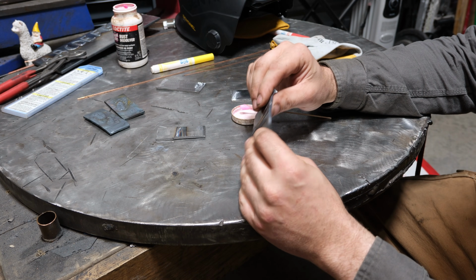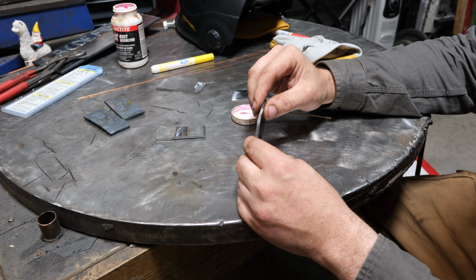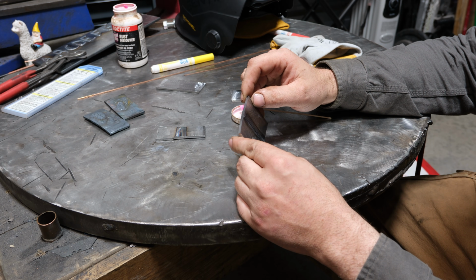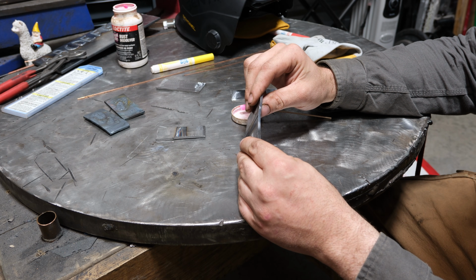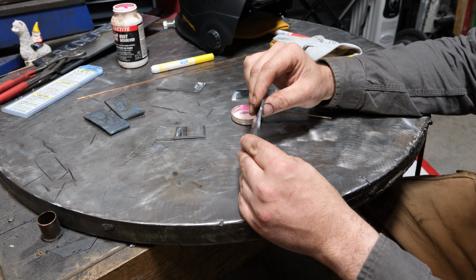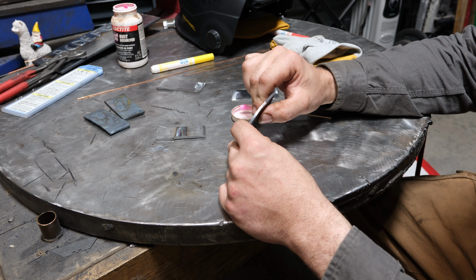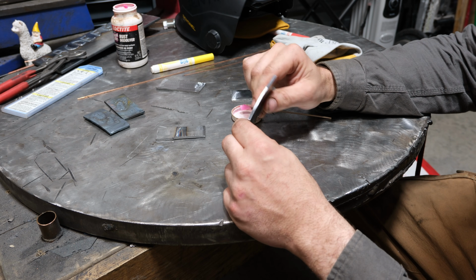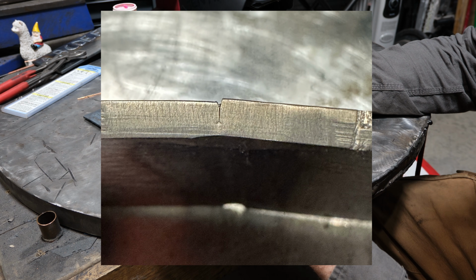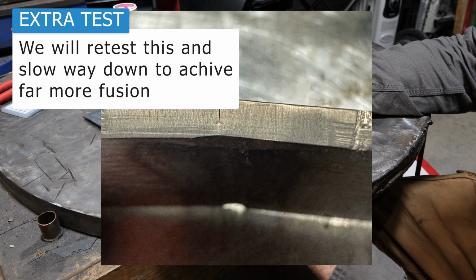So I did a cut and etch on this, and the etch is almost impossible to see, and that's because we didn't add any filler metal of a different alloy, so the etch doesn't really show the weld nugget per se. But what I ended up doing is bending the plate just enough to show the depth of fusion, and let's put a picture up and look at that right now. Now, as you can see, this fusion weld, despite on surface value looking like a decent weld, basically has no penetration whatsoever. This is only 3.2 millimeter, aka 1/8 inch plate, and we're not even, I'd say, about a quarter of the way through the plate at 120 amps. So that's virtually no penetration.